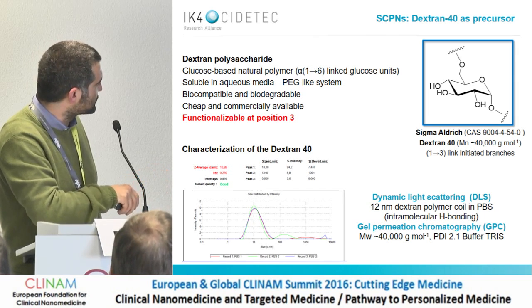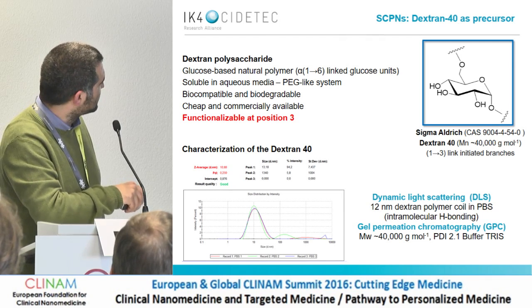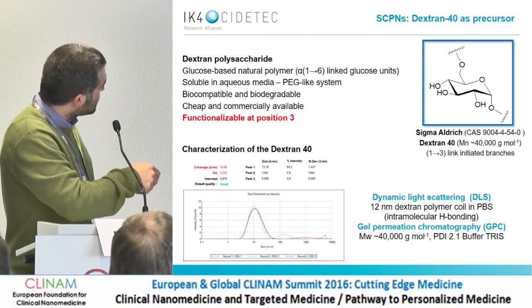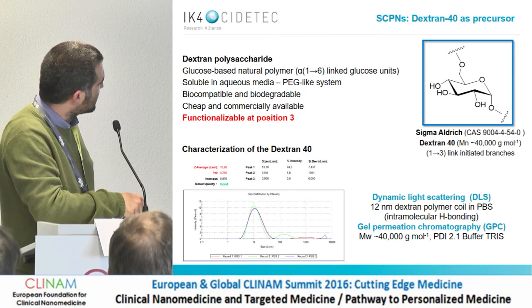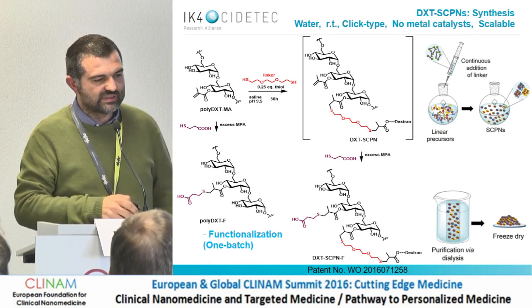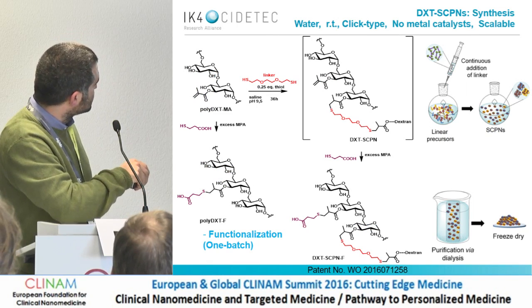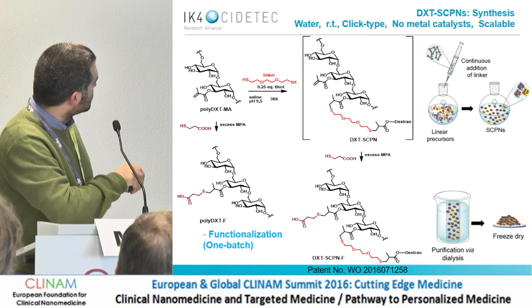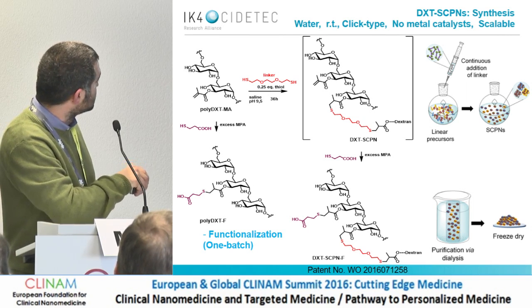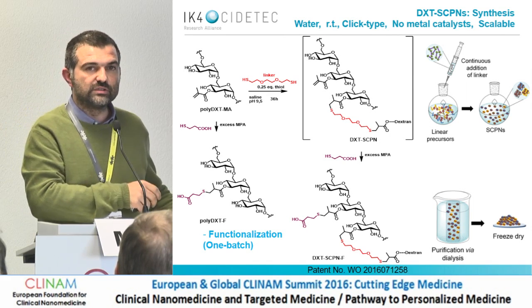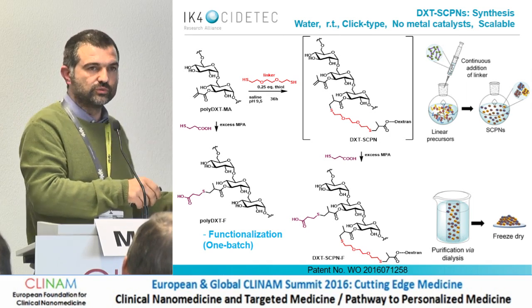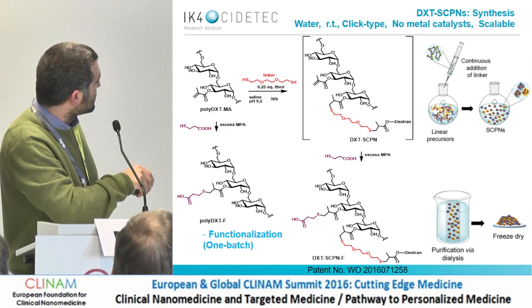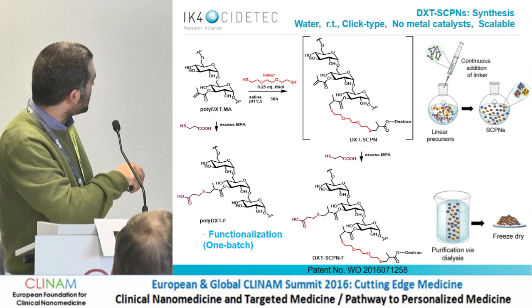This gives an idea of the dimensions of dextran 40 — there is a range of other molecular weight dextrans available, but we started with this one. Our protocol is based on functionalization at position 3 of the dextran polysaccharide with a methacrylate group. This precursor is soluble in water, so we work in non-highly-diluted conditions — 10⁻¹ to 10⁻² molar — which is quite unusual for this kind of synthesis. We then make a continuous addition of a dithiol linker, performing a thiol–Michael addition to the double bond.